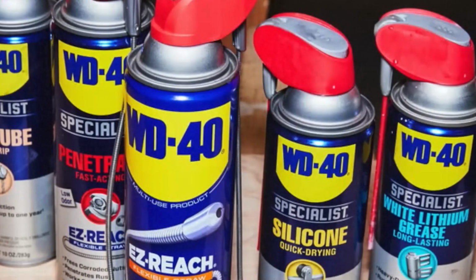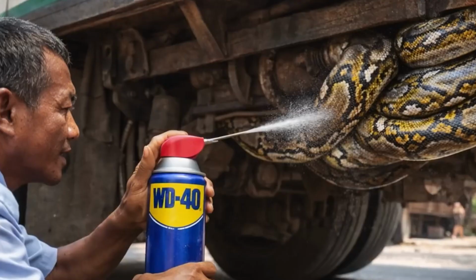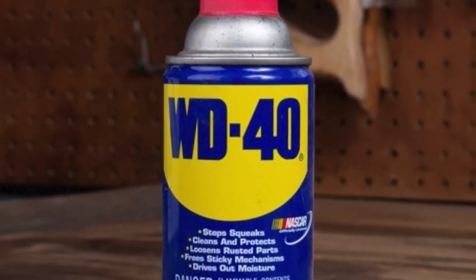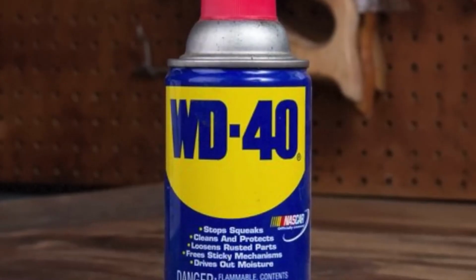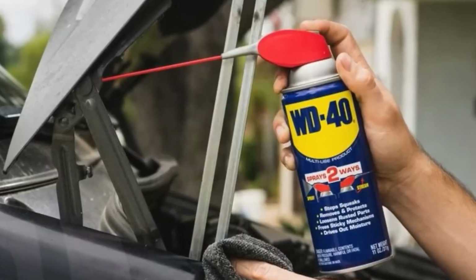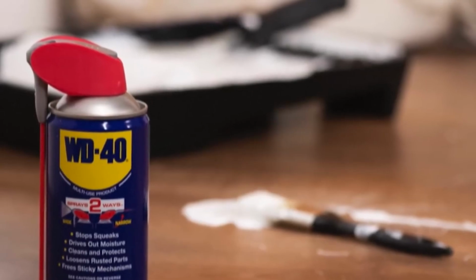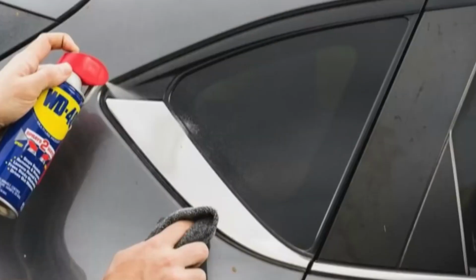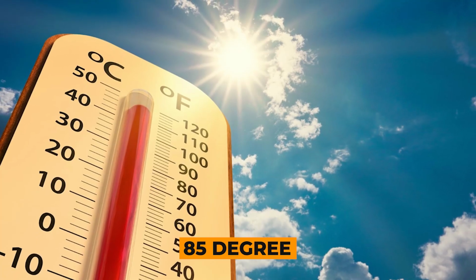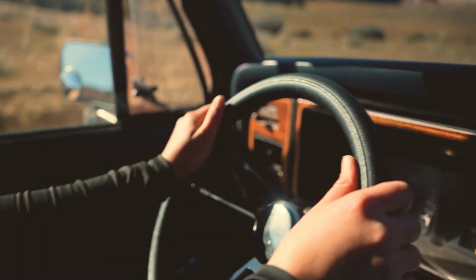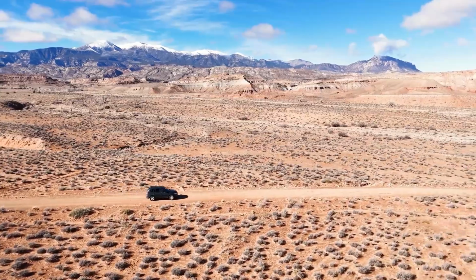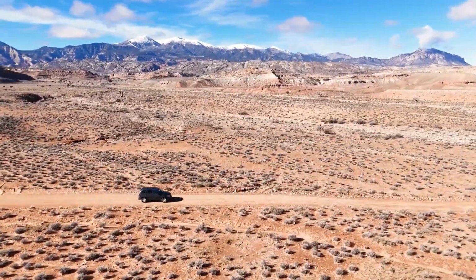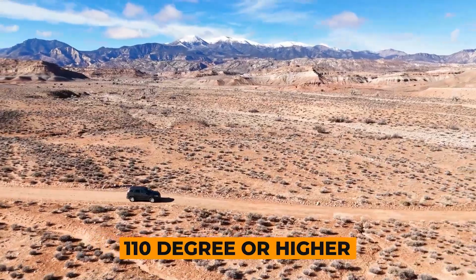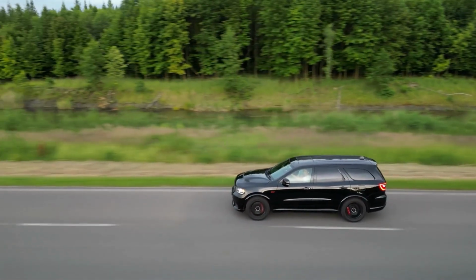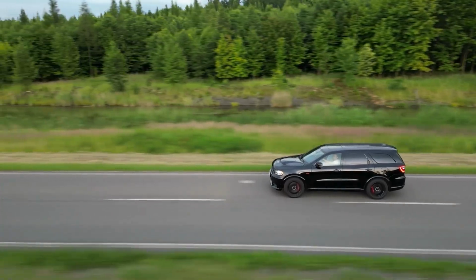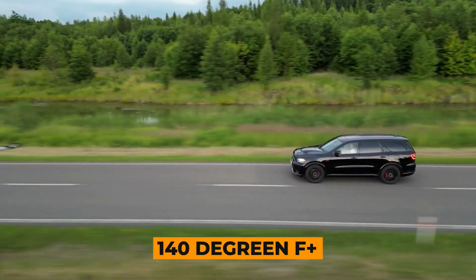And those new compounds aren't inert. They're reactive, they're acidic, and they're sitting directly on your clear coat's polymer surface. Now layer the heat on top of this, because that's what makes the real-world scenario genuinely dangerous. You might think it's 85 degrees outside, so your car is 85 degrees. That's not how it works. The air temperature might be 75, but your hood in direct sunlight can reach 110 degrees or higher. Dark vehicles absorb even more heat, and black cars in summer sun can see surface temperatures exceed 140 degrees Fahrenheit.